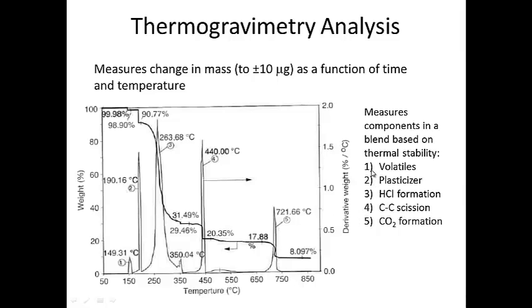According to the analysis of this polymer which happens to be PVC or polyvinyl chloride, this is the release of volatiles, possibly solvents that were present in the polymer during processing. Then at a slightly higher temperature we see another drop off and more mass is lost. This is due to the burning of plasticizers that are added to the PVC to make it more ductile.